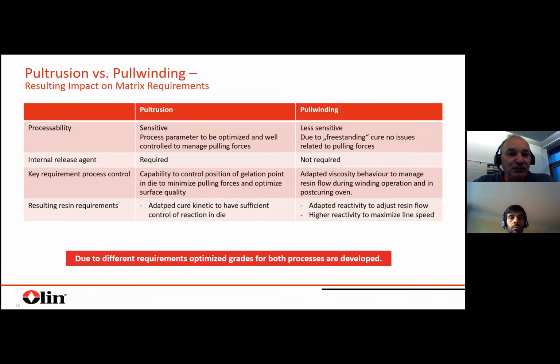Internal release agent: in pultrusion, it's required. Otherwise, you will have a significant issue with your pulling forces and/or the surface quality. In pull winding, as you have not really a closed mold, it's not required. The key requirement on the process control in pultrusion, as mentioned, is that you have to find a good spot for positioning the gelation point in the die to minimize the pulling forces and optimize the surface quality. But on the other hand, you will also optimize your output, so at the end, your line speed. So there you really need a well-defined way to do this.